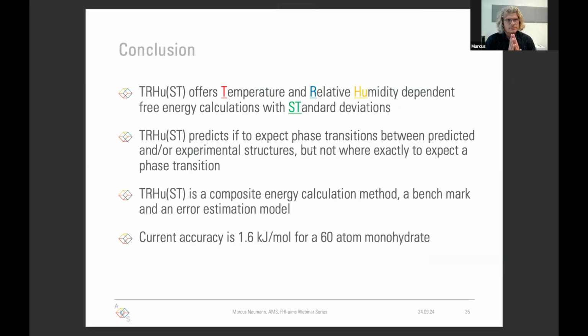Conclusion. So first of all, there is a method which offers temperature and relative humidity dependent free energy calculations with standard deviations. The acronym is TRUST, and this is heavily based on calculations with FHI-aims. Regarding predictions, the accuracy of predictions still has to be taken with a grain of salt. TRUST predicts if to expect phase transitions between predicted and or experimental crystal structures, but not where exactly to